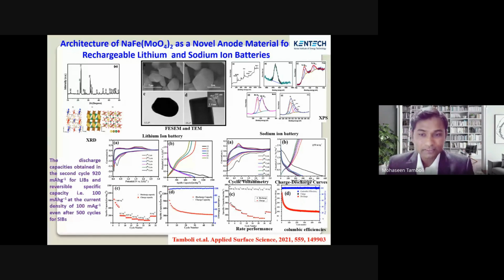This synthesized material we have also demonstrated for lithium ion battery and sodium ion battery. In the lithium ion battery, it's showing excellent performance, with 99% Coulombic efficiency even after 50 cycles at different current densities, starting at 50 milliampere per gram.